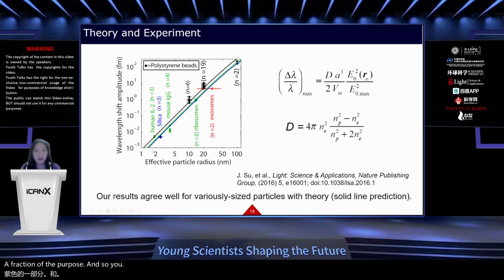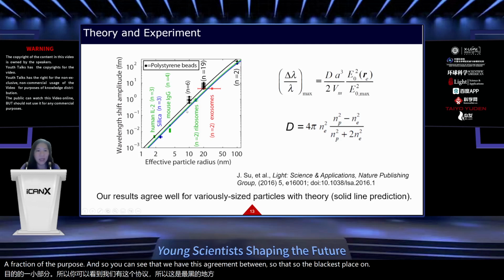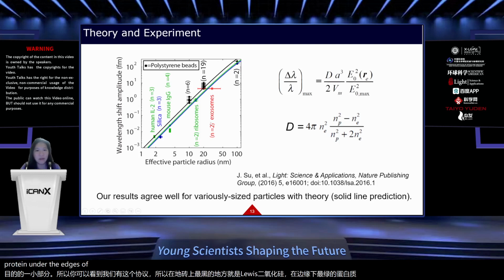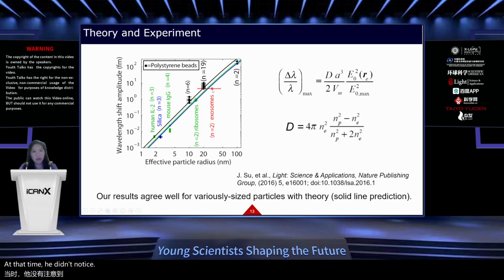And so you can see that we have this agreement, so the black is polystyrene beads, the blue is silica, the green is protein, and then the exosomes. At that time, we didn't know what the index of refraction of an exosome was, so we put it separately, although now we do know what the index of refraction of an exosome is. And so you can see that we agree with theory over a wide range of sizes and different materials.